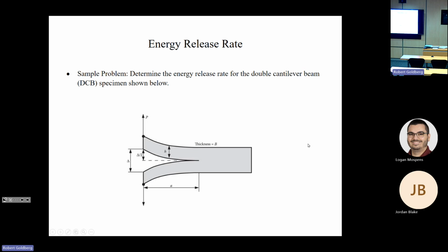So now for a practical application of this, what we're going to do now is determine the energy release rate for this double cantilever beam specimen here, where we have a thickness equal to B and we have an opening displacement delta between the top and bottom surfaces, and we have our crack length equal to A.